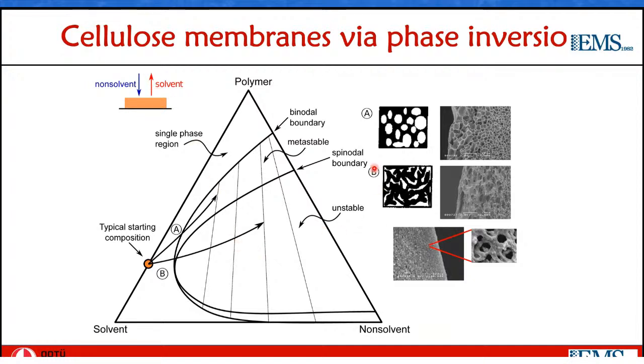As very broad examples, if phase separation occurs in the metastable region by nucleation and growth, you get more or less these cellular morphologies, whereas when you have phase separation in the unstable region by spinodal decomposition, you have more bicontinuous morphologies. The actual picture is, of course, much more complicated than that, but you can basically tune the membrane morphology to be a symmetric or an asymmetric membrane, microporous, macroporous, and alike, by controlling the starting composition and the rates of non-solvent and solvent diffusion.